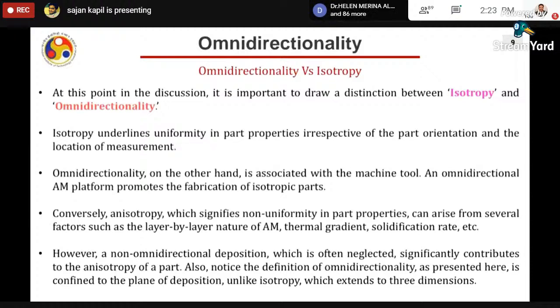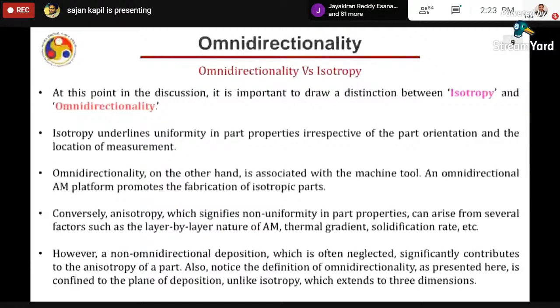Isotropy underlies uniformity in the part properties, irrespective of the part orientation and location of measurement. While omnidirectionality, on the other hand, is associated with the machine tool. An omnidirectional AM platform promotes the fabrication of isotropic parts. Anisotropy, which signifies non-uniformity in the part property, can arise from several factors such as the layer by layer nature of additive manufacturing, thermal gradient due to the scanning, and solidification rate. So there are several reasons for getting anisotropy in the additively manufactured part.